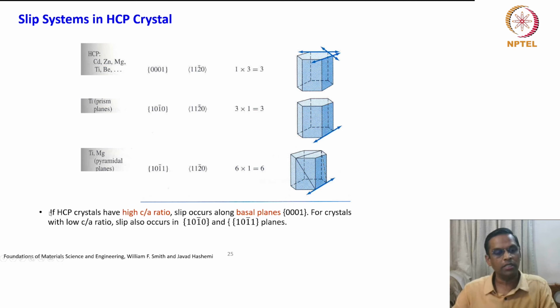But the problem with HCP is that it is very sensitive to the c by a ratio. If HCP crystals have a high c by a ratio, slip occurs along basal planes, that is 0001 type of planes. For crystals with a low c by a ratio, slip also occurs in the prism planes. Okay, so this is one thing we have to remember. So you see that compared to FCC, both BCC and HCP do not have highly dense planes. That's the bottom line.